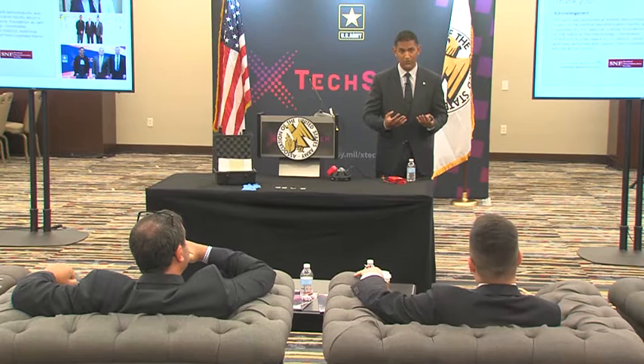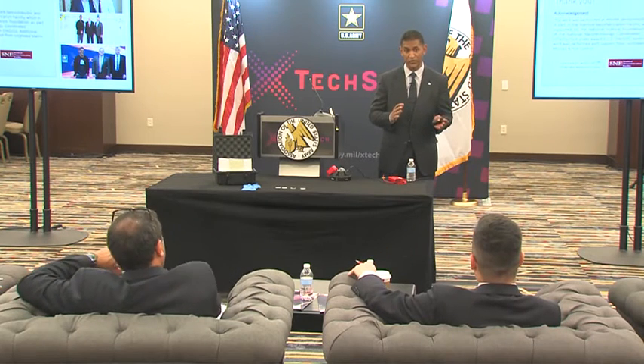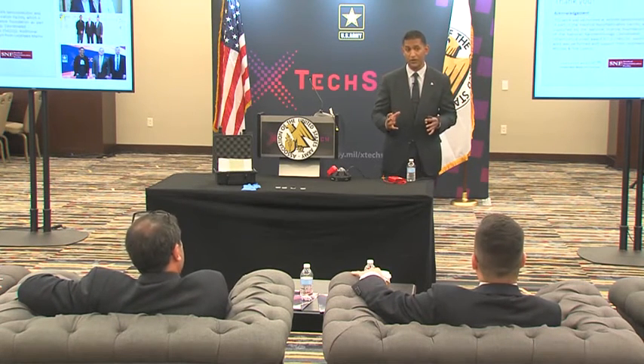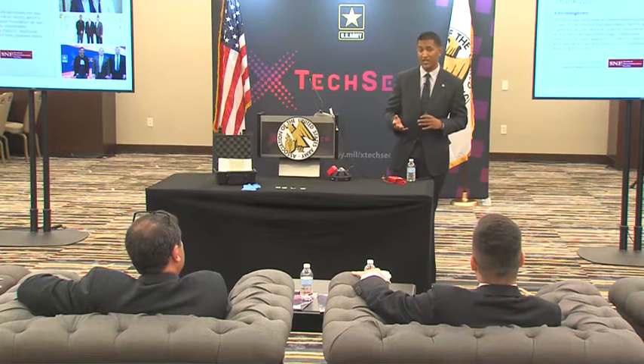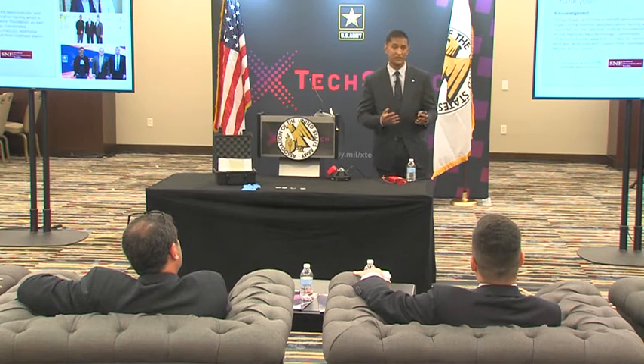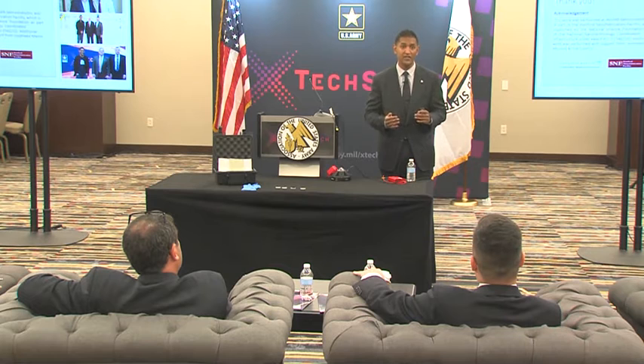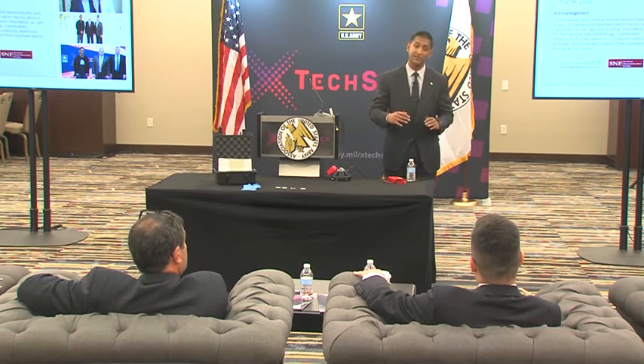What is the relationship between the thickness of the various layers, the FGO and diamond layers, and the protective and absorptive properties, both in the near IR and in the RF? So we actually have a multi-layer intellectual property, so we're able to tune the transmissivity of the material without significantly impacting the hardness, so that's on the diamond side. On the FGO side, we want to keep this less than 10 nanometers. We want to keep this atomically thin. The reason being, then, is you have a highly uniform single sheet without any serious effect to the optics.